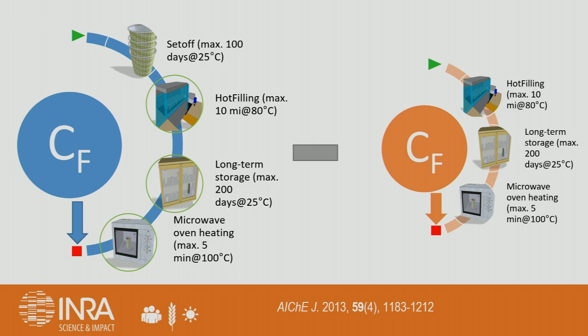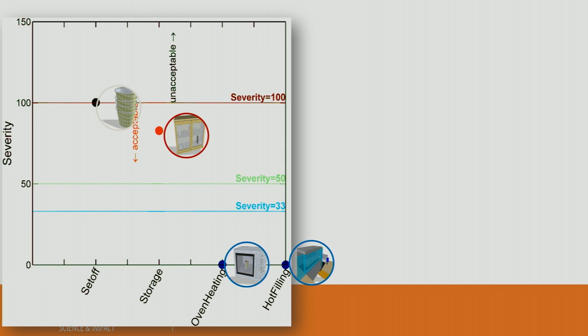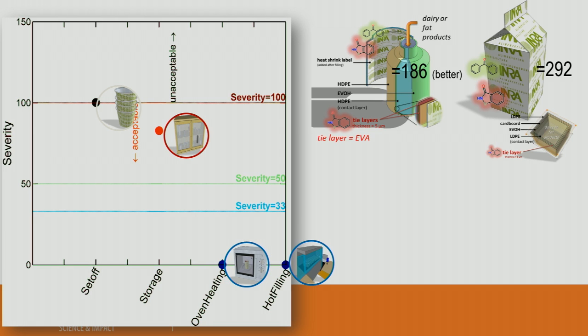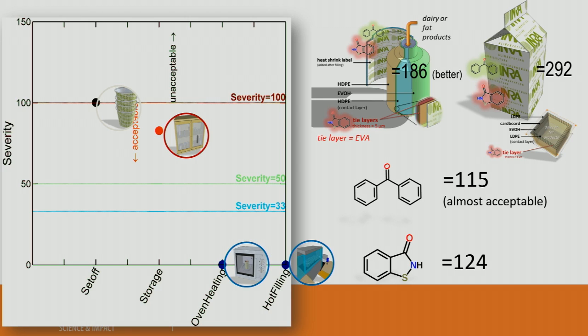The correct way to evaluate the contribution of a given step is: you evaluate the concentration in the food at the end of all four steps, then compare with the same process when you remove that step — run the three remaining steps and compare whether the two concentrations are the same or not. If they are the same, that step is not significant. If they are different, that step was important. And if you do this, you will demonstrate — as shown in this Pareto chart — that the most important step is the stacking, because you redistribute the contaminant by putting the inner layer of the cap in contact with the external printed layer, creating a shortcut.